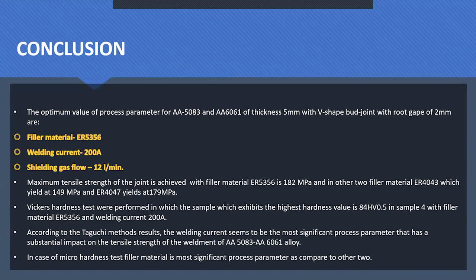Now coming to the conclusion part. In the case of tensile testing, the optimum value of 182 megapascal is achieved in the specimen with filler material 5356, welding current 200 ampere, and shielding gas flow 12 liters per minute. In the case of the other two materials, as we discussed above, the highest UTS value for filler material 4043 is 149, while for 4047 the value is 179 megapascal. When it comes to hardness, the highest Vickers hardness value achieved is 84, in the specimen with filler material 5356. According to the Taguchi optimization method, the most dominating factor in tensile testing was welding current, while in micro hardness, the most dominating factor is filler material. Thank you.